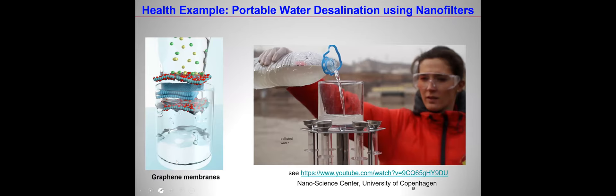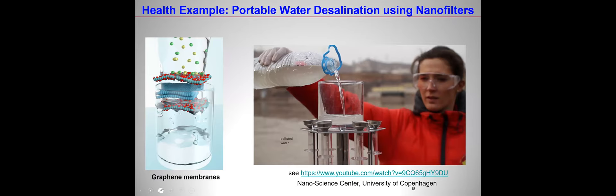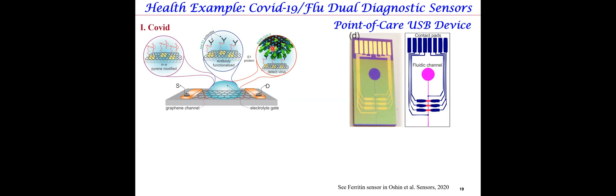Another example, we're working on diagnostic sensors for the coronavirus. As you all know, this is a global public health issue. We're using graphene as a diagnostic sensor. Graphene is very sensitive to everything. What we're doing is functionalizing it with the antibody of the coronavirus. These antibodies make it extremely selective and bind to the coronavirus. If you take a sample from saliva or a nasal swab, that binding will register as a distinct change in the electrical resistance or impedance of the material. This way, you can detect the presence of the virus.